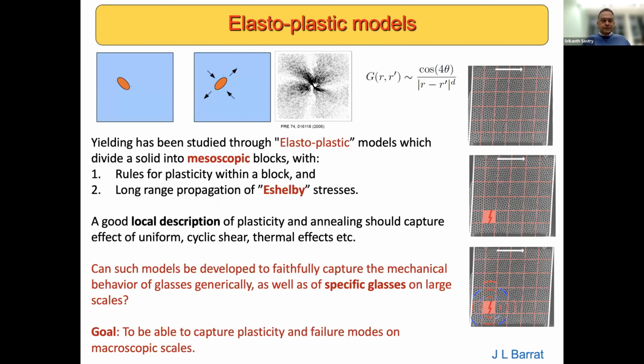Okay, now how does one go about modeling this behavior? As I already mentioned, one can think of plastic response as being composed of plasticity within a small region or volume of the glass that I'm looking at, and a long-range propagation of Eshelby stresses. And so a good description of the local plasticity combined with the well-understood propagation of stresses should give you a model description that faithfully captures the mechanical behaviors of glasses. So the goal is to build these models of local plasticity that are good enough to do the job.